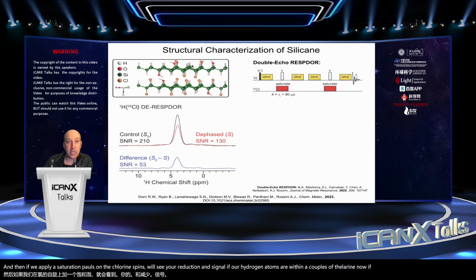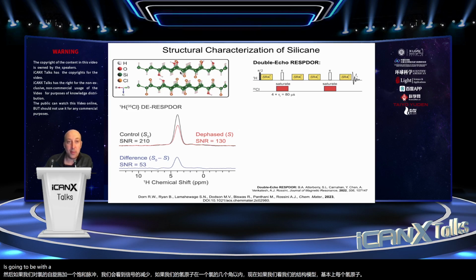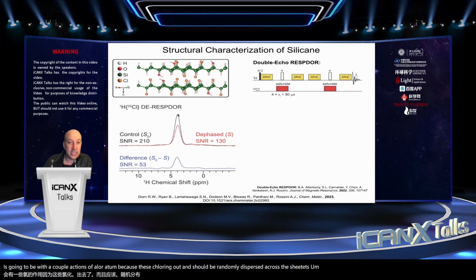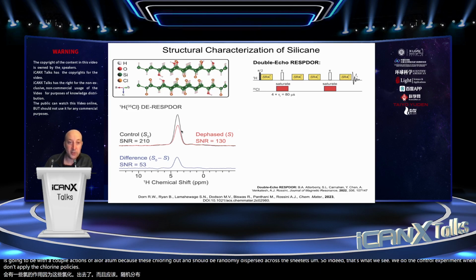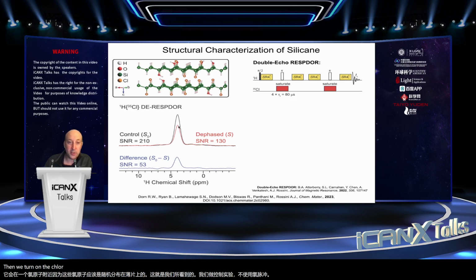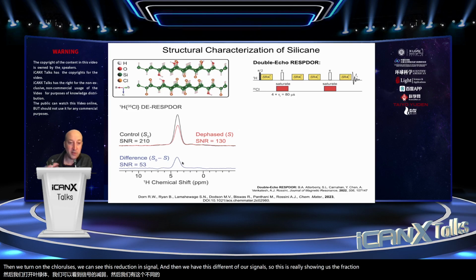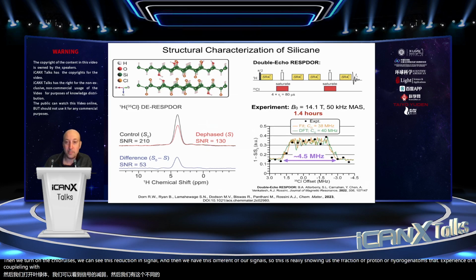Now, if we look at our structural model, essentially every hydrogen atom is going to be within a couple angstroms of a chlorine atom because these chlorine atoms should be randomly dispersed across the sheets. So indeed, that's what we see. If we do the control experiment where we don't apply the chlorine pulses, then we turn on the chlorine pulses, we can see this reduction in signal, and then we have this difference NMR signal. So this is really showing us the fraction of proton or hydrogen atoms that experience a magnetic coupling with chlorine.